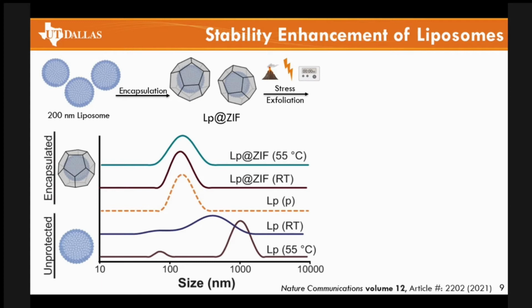As we see from this dynamic light scattering curve, whenever we had the ZIF coating protecting the material, the size, the dispersity didn't really change. As you can see, we heated up the liposomes at 55 degrees Celsius, and in the presence of the ZIF coating, the material retained its dispersity, just like the pristine liposome. Whereas when we had these materials either just sitting at room temperature for 48 hours or heated at 55 degrees Celsius for 15 minutes, without the ZIF coating, they greatly suffered, as we see. Their size heavily increased as a function of lipid fusion or aggregation.